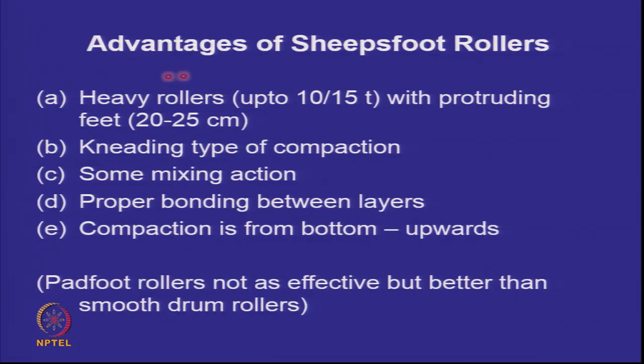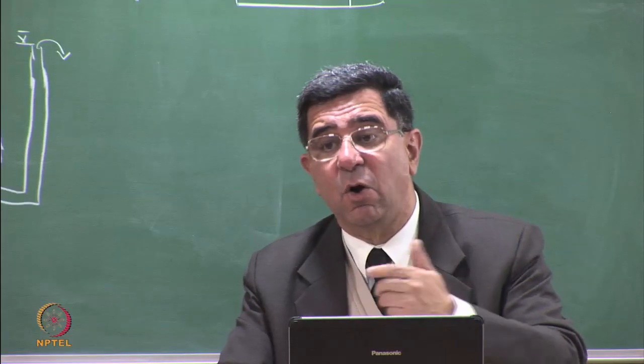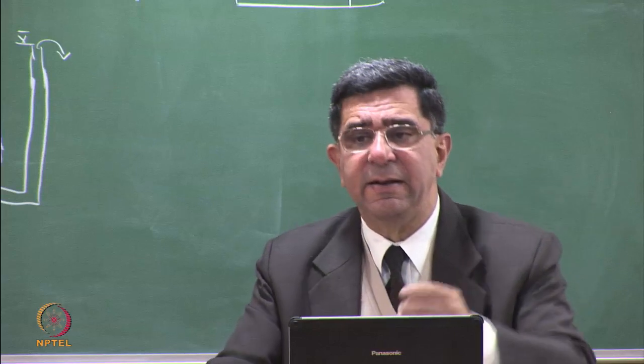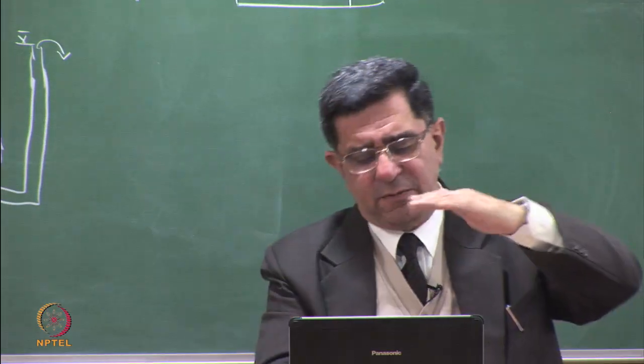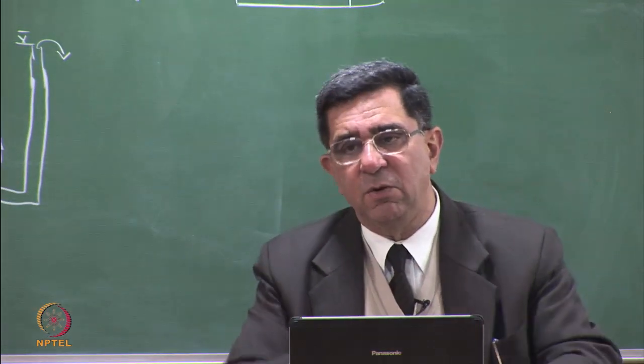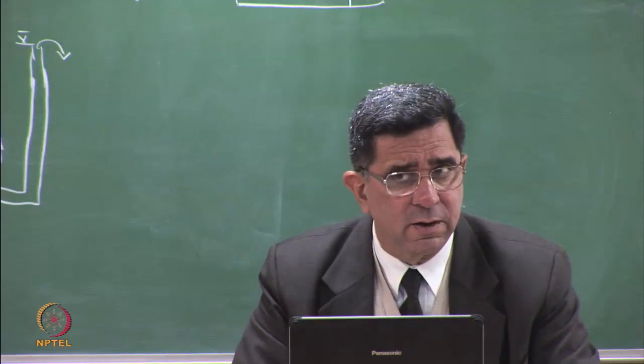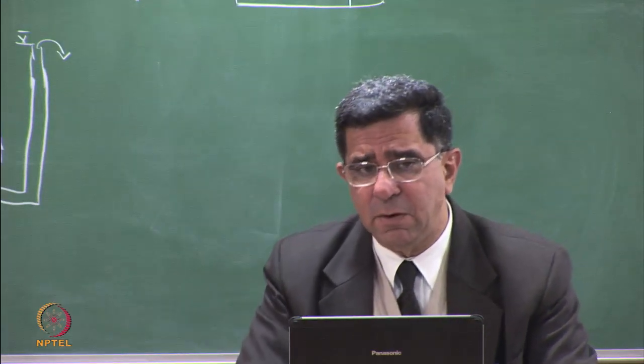So advantage of using sheep's foot roller, you can use heavy rollers with protruding feet. You get kneading type of compaction which breaks down clods. The kneading action has some mixing action also, so water gets mixed properly. Take a clay sample, 25 centimeters thick, you put some water on top and you run a smooth steel drum roller on it. The water will not even penetrate properly into the soil.